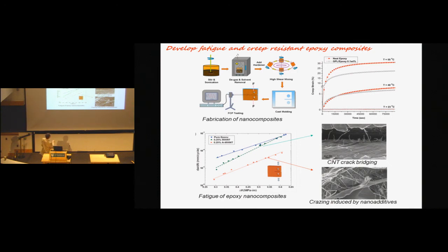So you get a much tougher material which actually resists fatigue more, and this is shown in this plot. This axis represents crack growth rate, da/dN, right? The speed at which the crack grows, and the horizontal axis is the stress intensity factor amplitude, that is how much you load the crack, okay? So as you load more, of course the speed goes up. But look at this difference. This blue curve corresponds to pure epoxy. This is how fast cracks grow in pure epoxy. When you consider this material, the one in which the physics is being changed, you get the red curve. So you see, you get an order of magnitude improvement in fatigue properties just by adding 0.1% by weight of nanoadditives. Okay.